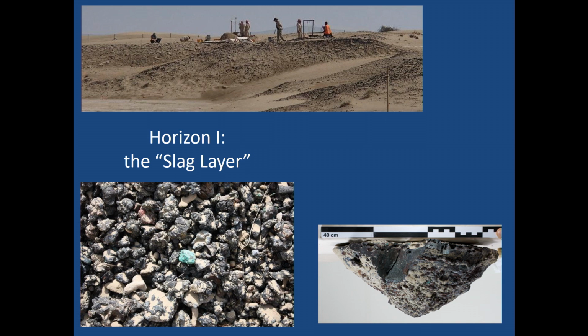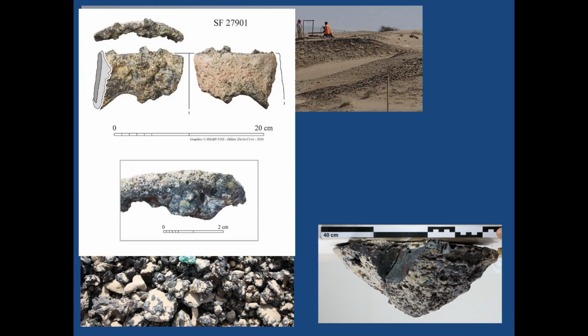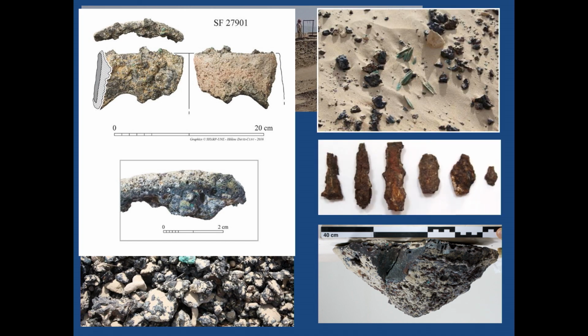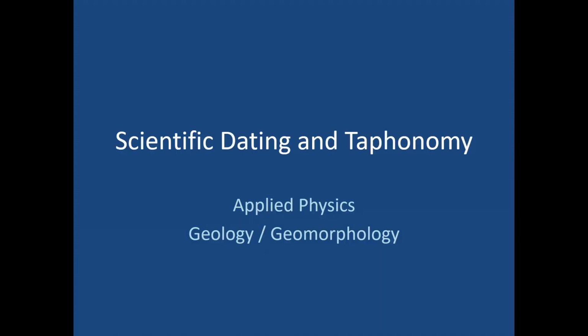We've got large lumps of tap slag, which was clearly tapped out of a furnace at some point and collected into a pit during the copper smelting process. We've got pieces of ceramic or furnace wall, which tell us something about the technology of copper production at the site. But we've also got material that looks like Horizon 2. We've got arrowheads in bronze. We've got iron artefacts, the handles of what look like iron swords and these kind of things, which are coming out of these upper deposits as well. So broadly, that's the sequence that we've got.